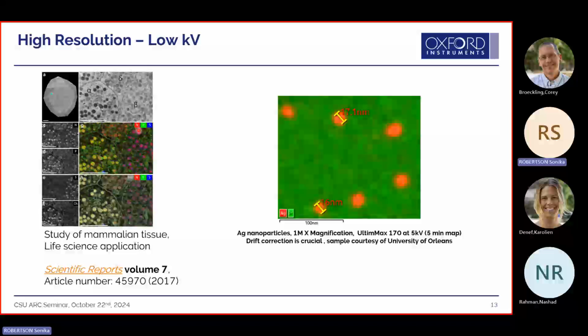Another thing is the system comes with 5 forescatter diode detectors. So normally in an SEM, when you do the 70-degree tilt, you can only see part of the sample in focus. With these forescatter diode detectors, you will actually see the entire field of view in focus, and you can image those, see what it looks like, and take images prior.